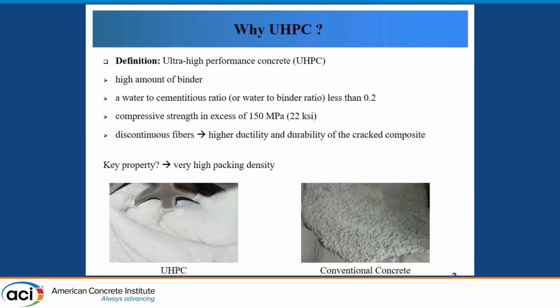So why UHPC? Most of us already heard about UHPC. It is a cementitious composite with relatively high amount of binder in comparison to conventional concrete. It is designed to use a water to binder ratio of less than 0.2 for its compressive strength in excess of 150 megapascal, or say like 22 ksi. The addition of tailored discontinuous fiber reinforcement leads to significantly high ductility and durability of the cracked composites. The key for the strength and durability properties is a very high packing density of the matrix.